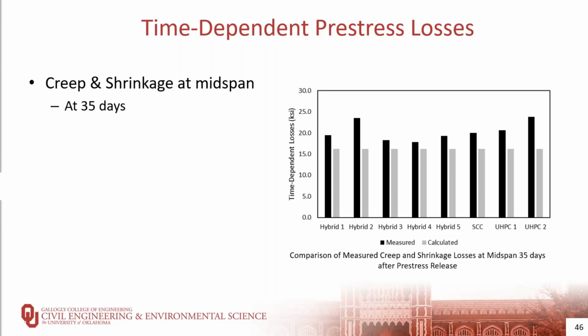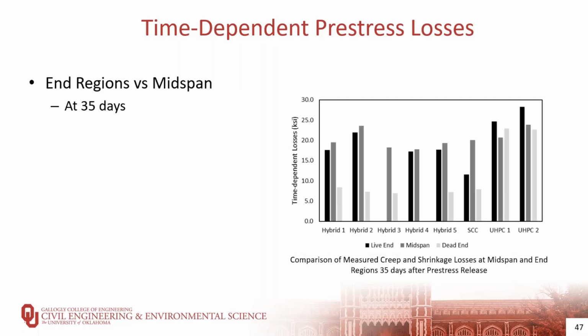That suggests similar behavior in the pre-stress losses between the hybrid and the full SCC girders for the time-dependent losses. The behavior of the long-term losses at end regions was similar to the behavior of the immediate losses at end regions for all the girders. From the figure here on the right, the hybrid girders' UHPC end region and midspan exhibited similar time-dependent prestress losses. Again, this is an indication of the shorter transfer length that the UHPC has compared to the conventional concrete.